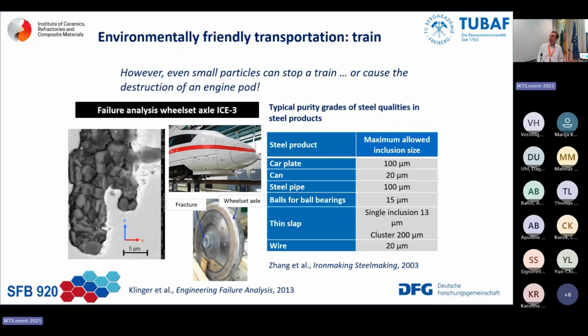Somebody would say, what was triggering this? It was an accident that happened with the ICE train in 2008, where very dense, fine aluminas in the range of 200 up to 400 micrometers could not be removed out of the wheel, and so we had the damage. I suppose for 8 months, the ICE train was not moving in the whole of Germany. This was good for us because we got a project.